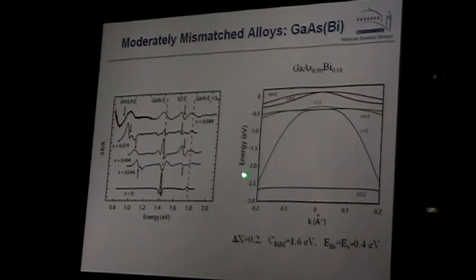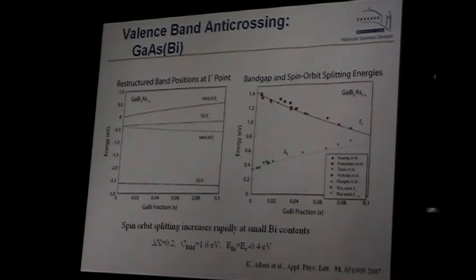One interesting aspect of this system is that you have spin-orbit splitting here. Bismuth has a very large spin-orbit splitting because it's a very heavy element. So what bismuth produces very quickly is a huge increase in the spin-orbit splitting, and this is something which was not expected. The band gap goes down as expected because the valence band edge is pushed up.